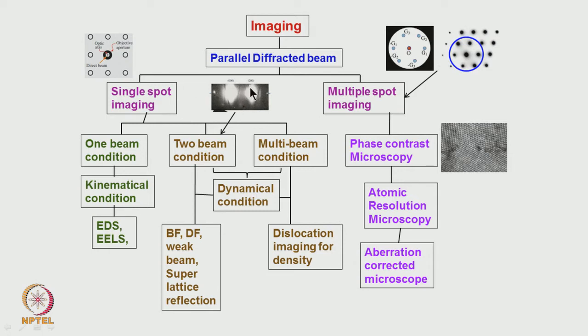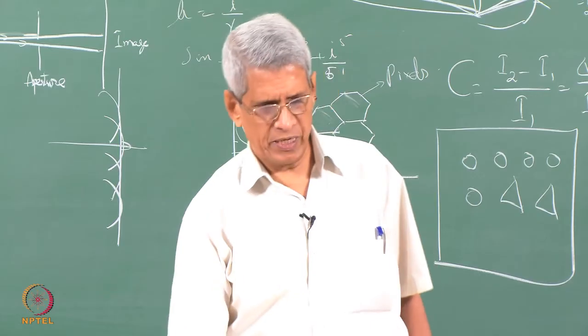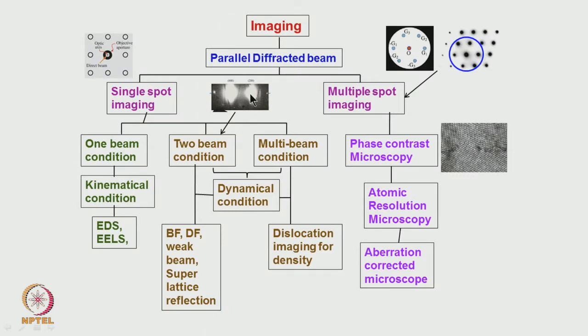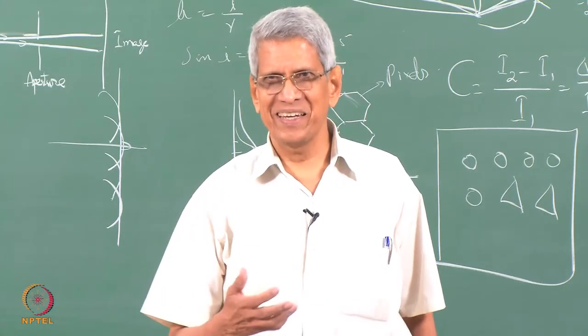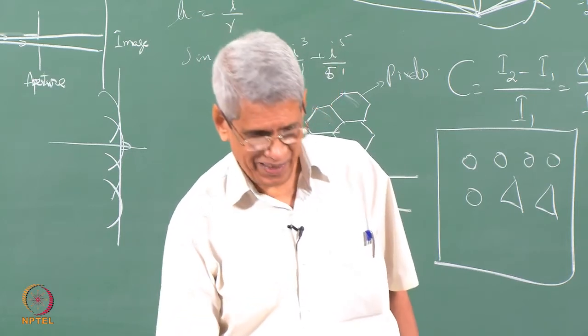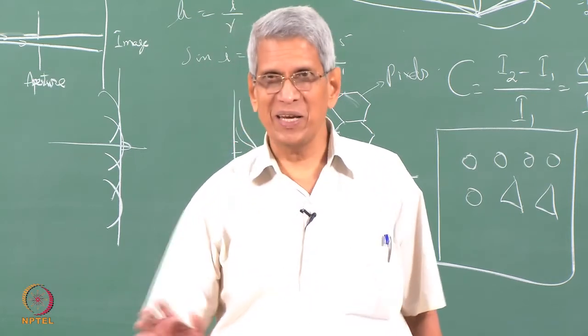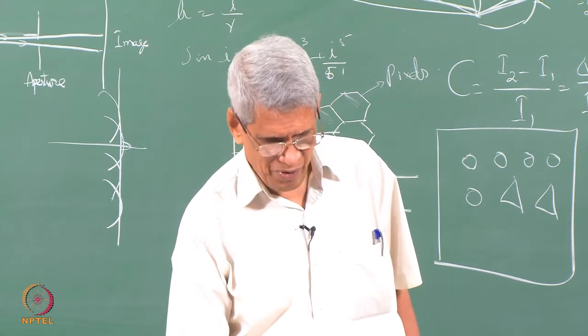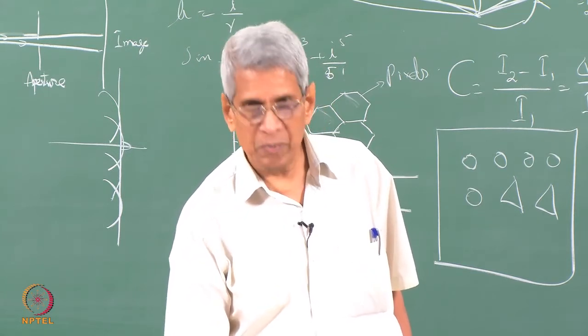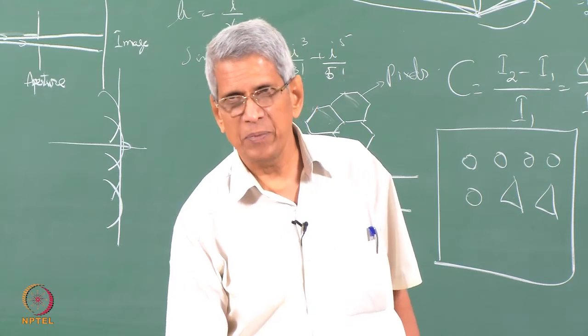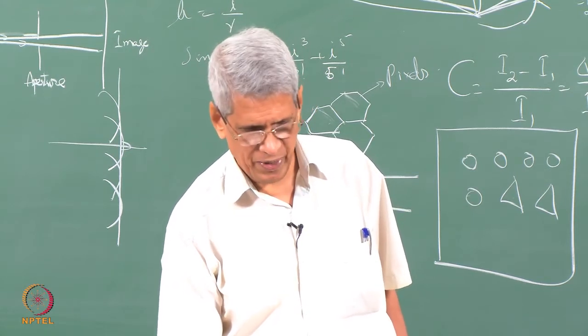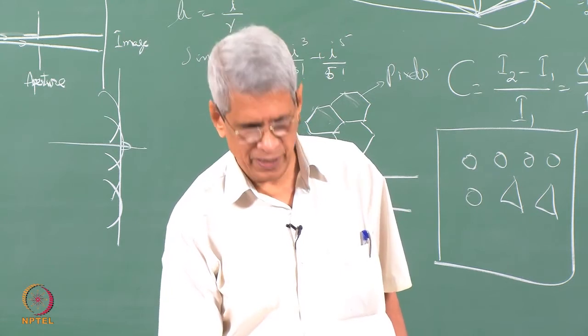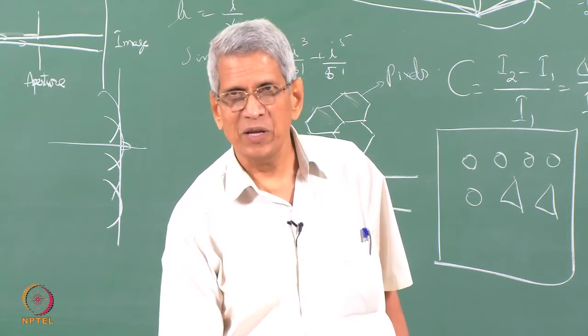Because we know that when a defect analysis is being done, depending upon which type of g vector is being used, the defect can be present or it can be absent. It is not that the defect is absent, but in the image we do not see it. That does not mean that the defect is not there. That is especially important for dislocation imaging, and that is where we have to be very careful. If you use a multi beam condition, one may satisfy g.b equals 0, another will not. Because of that, we will be able to image all the dislocations simultaneously so that we can get the true dislocation density.